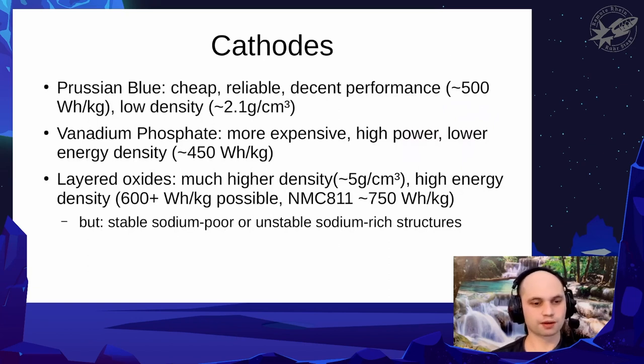Sodium ion batteries don't just need anodes; they also need cathodes. The cathode is the core of the battery. Actually, that's where all the chemistry happens. And Prussian blue, we talked about this. It has a very decent performance. The material itself, if you only had the cathode material, is 500 watt hours per kilogram in energy density, but it has a low density. It's only 2 grams per cubic centimeter, and that's quite low.